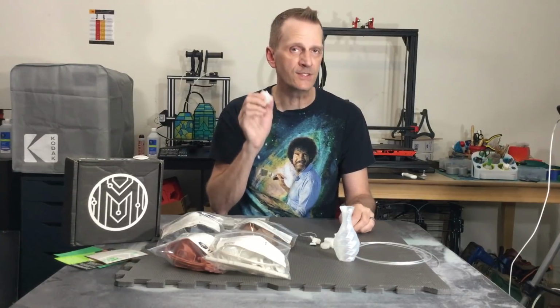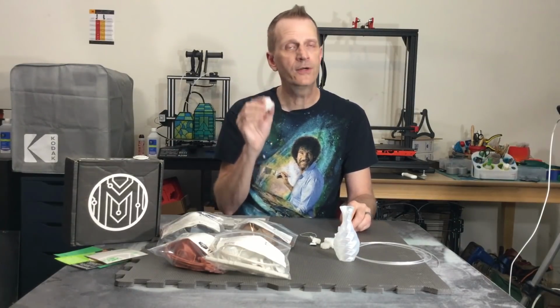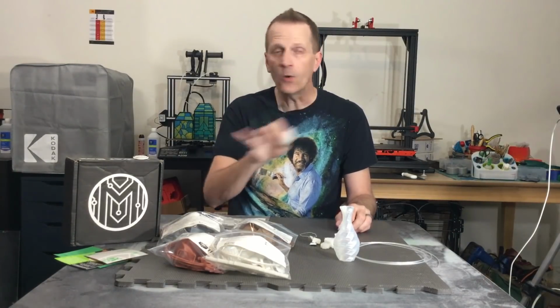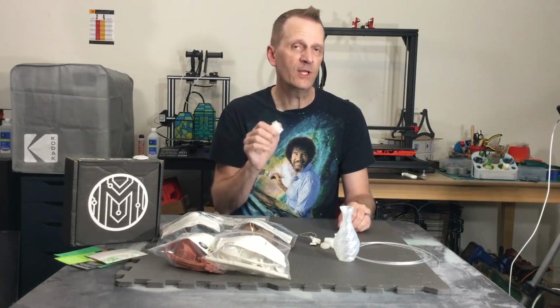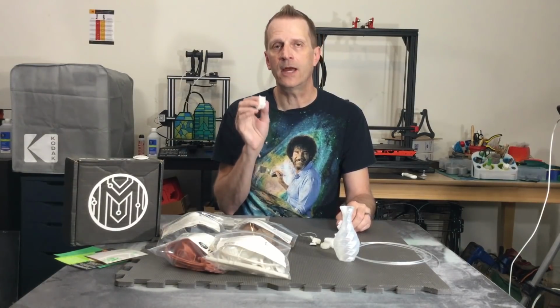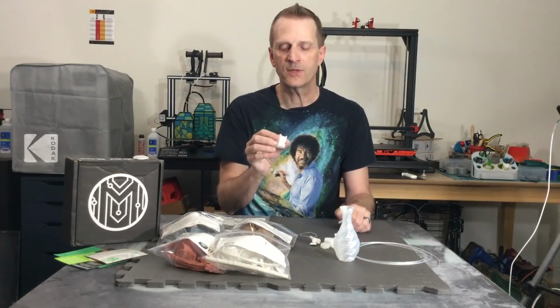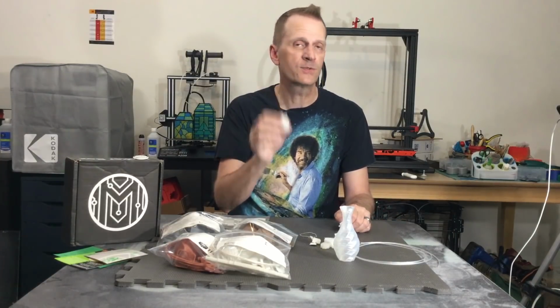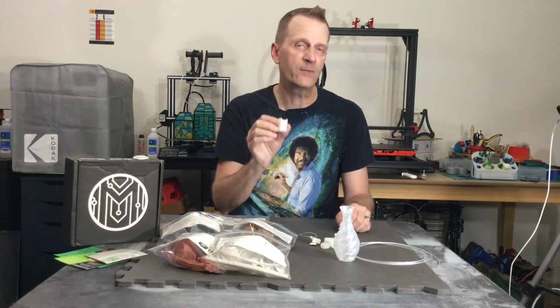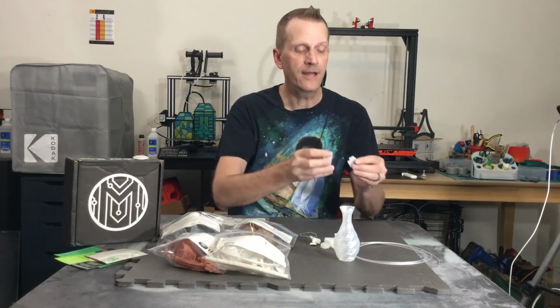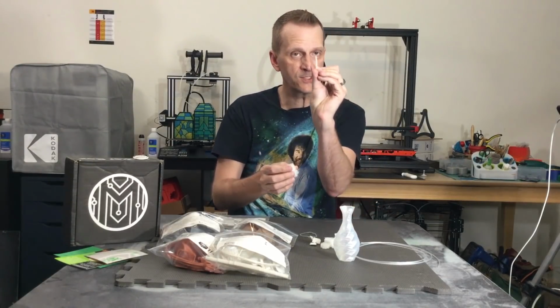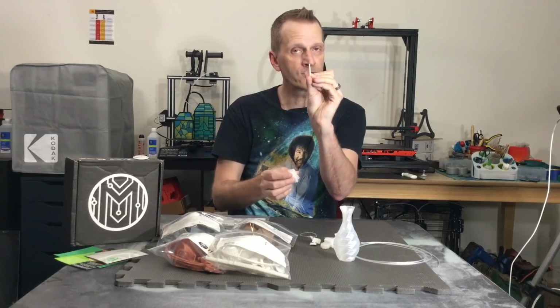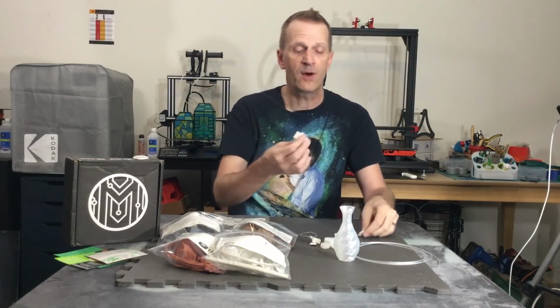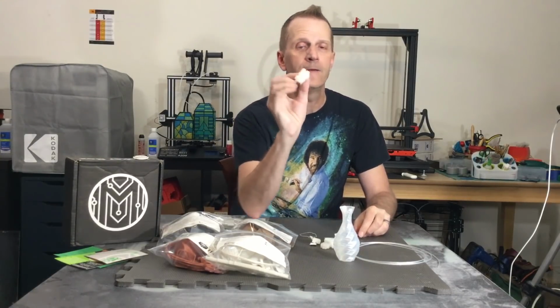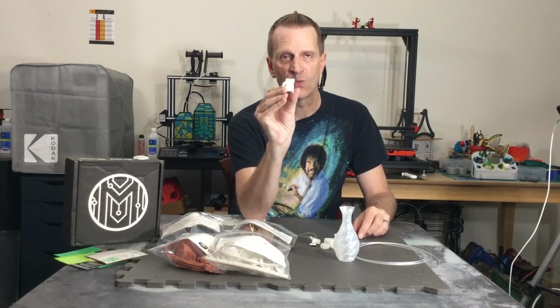Now, I did increase the temperature up to 235 C, no cooling whatsoever, 40 millimeters per second with the first layer at half speed, so 20 millimeters per second, 3 top layers, 3 bottom layers, 3 perimeters, and 25% infill on this particular model. Now, the raft printed out perfectly, but it started to warp about 3/4 of the way through the print, so I thought for sure it would pop off, but it didn't.